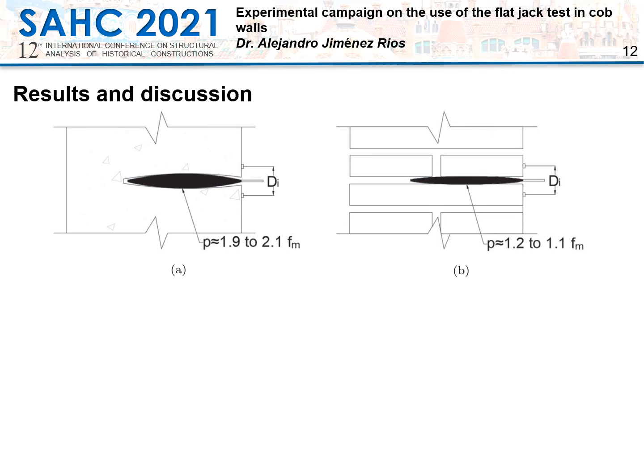As can be observed in the sketches of this figure, which presents the original distance between control points Di being recovered, the deformation at the flat jack centroid in the cob wall, figure A, is relatively big in comparison to the deformation suffered at its edges, whereas the flat jack's deformation in the masonry wall, figure B, is more uniform. It is worth noting that the strain values of the curves observed in slide 10 for the results of the double flat jack test are counterintuitive.